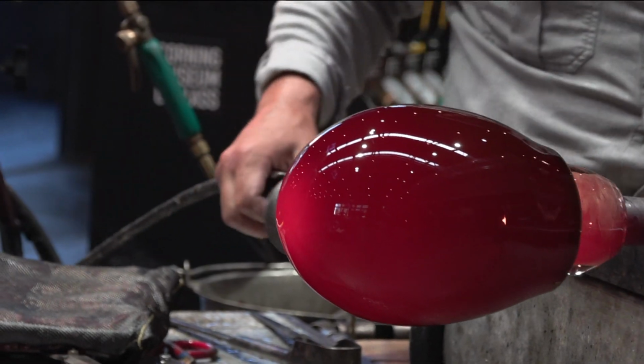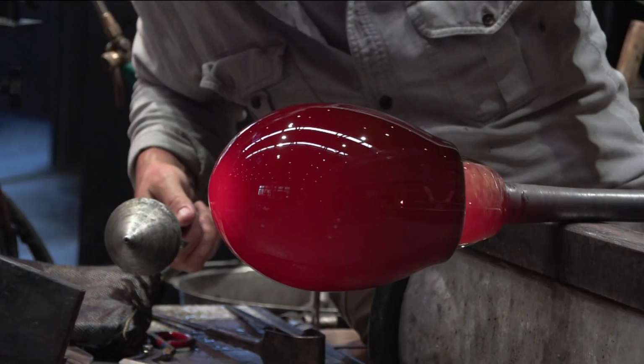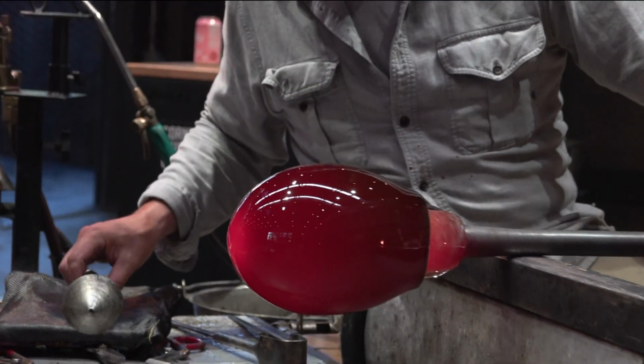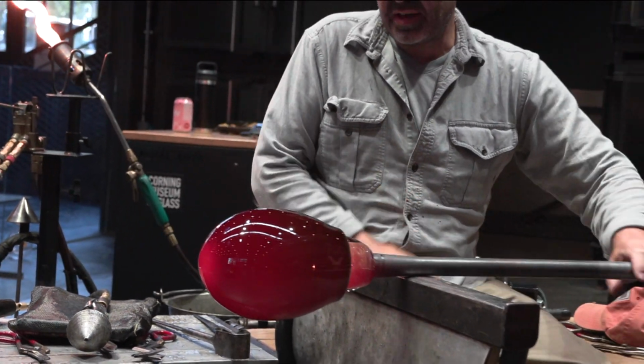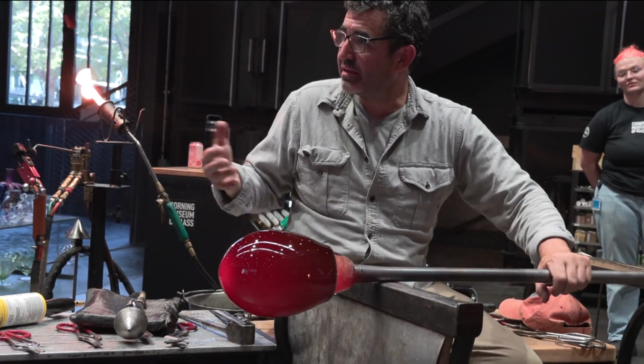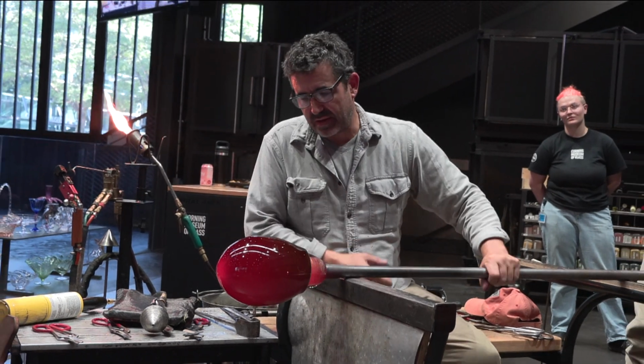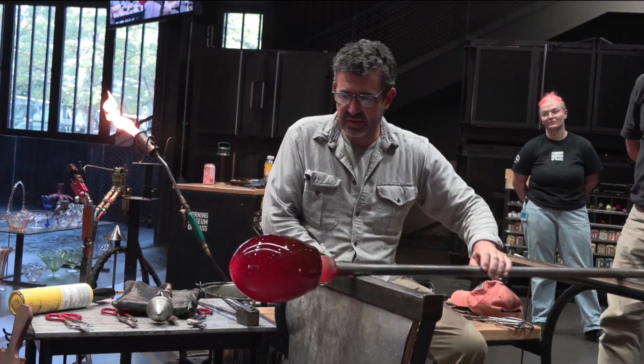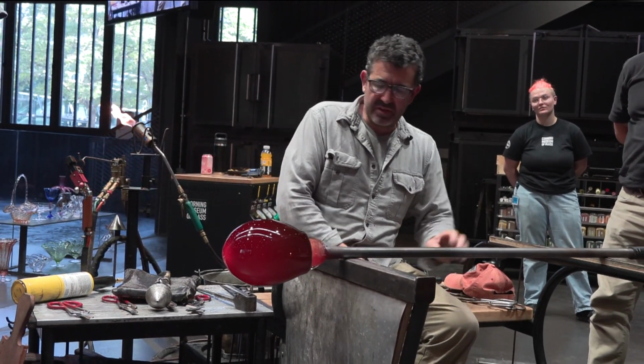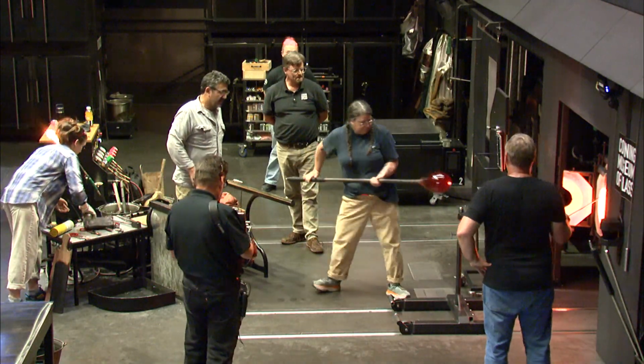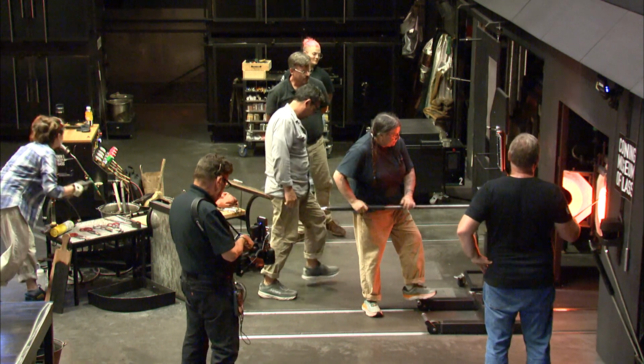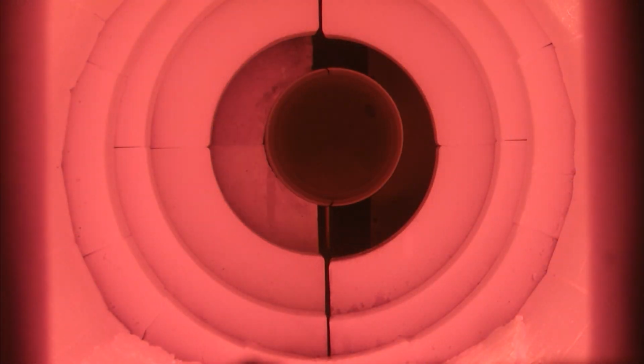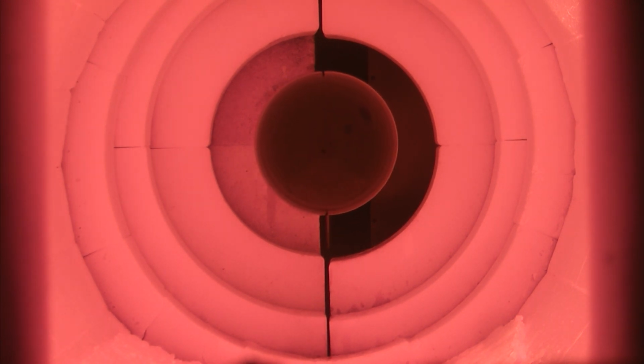All right, so they puffed this up a little bit. There's a bit of discussion going on. They're going to want to gather over this at least a couple of times. And so I heard Michael say, I don't want to blow this up too much. If we get the glass too thin, and then put that glass down into an oven with 1,000 pounds of glass in it, and try to turn that really thin glass in a really hot pool of glass, the glass is going to start to twist inside that. We're not going to be able to even bring it out sometimes.